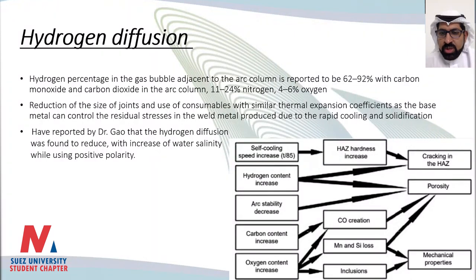the microstructure. Also, if you have oxygen content increase, it will react with the carbon and form carbon dioxide also, or carbon monoxide, and it can also react with the manganese and the silicon we just talked about. And then we're going to have also inclusions, and all that will affect the mechanical properties of your weldment.